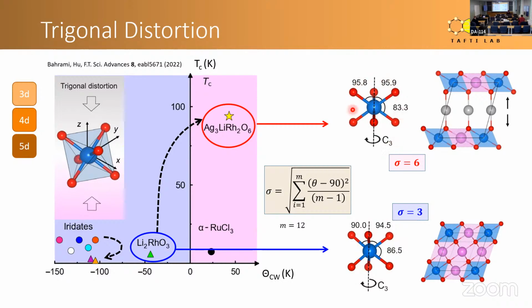Even if you just try to focus on this image at the bottom and then this image on top and toggle between them yourself, just look down and look on top, you will see that the oxygen atoms are actually squashed against the rhodium atom. If you do it a few times for yourself, go down and up between these two images, you'll see that the oxygen atoms are squashed against the rhodium atom. And that is the trigonal compression.